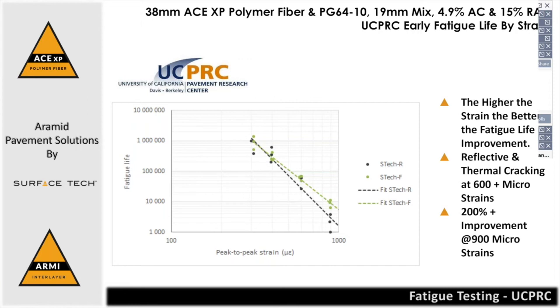Well, what's important on these curves is that the flatter the curve, which you see moving from the black or the dark gray to the light green, the more that product becomes less sensitive to movement in the pavement. If I could have the optimum results, I would have an absolutely flat line.